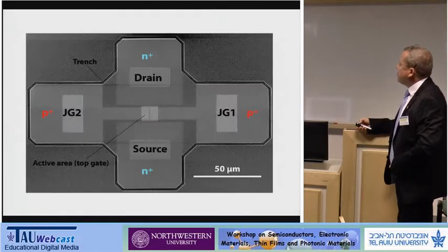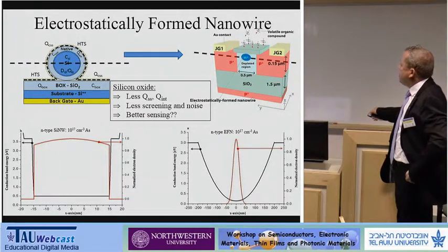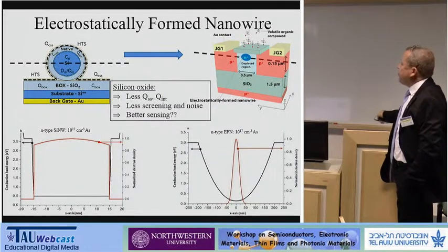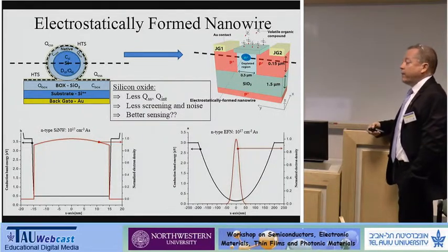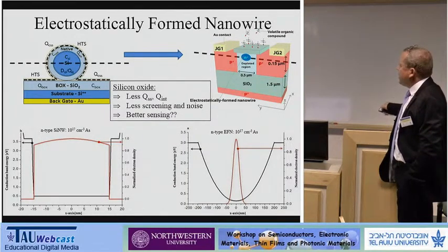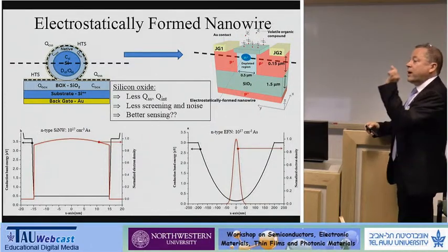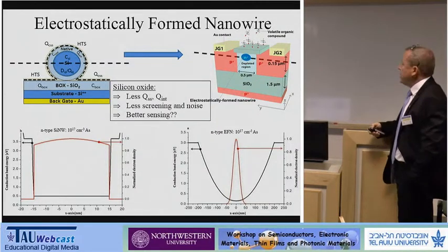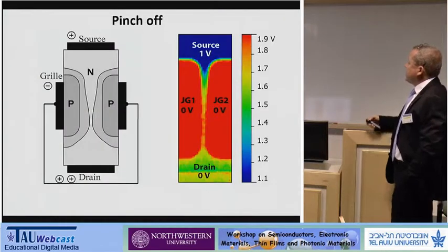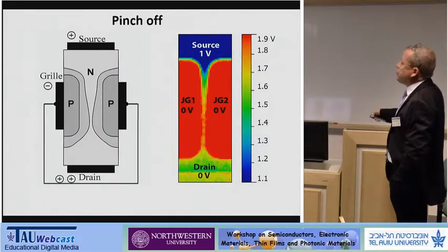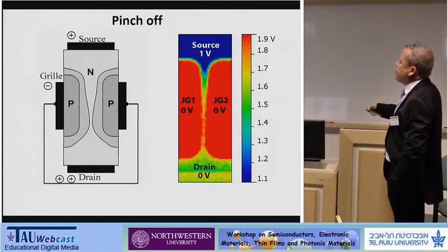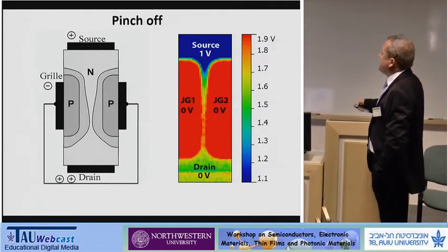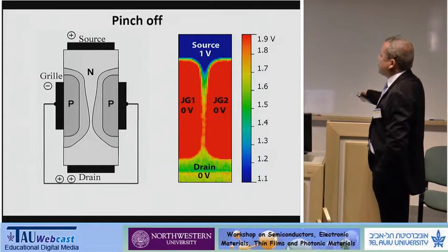So what we really measure, if I go back to here, is this. From a top view, we measure this. We don't measure the carrier distribution. So by measuring this and fitting it to a calculation, we can obtain the virtual nanowire carrier distribution and concentration. This is the idea. And even nicer, this is a measurement, and you compare it to a textbook. This is very nice to show to a student. This is a JFET from a textbook, and it really looks similar to our measurement. This is a measurement.